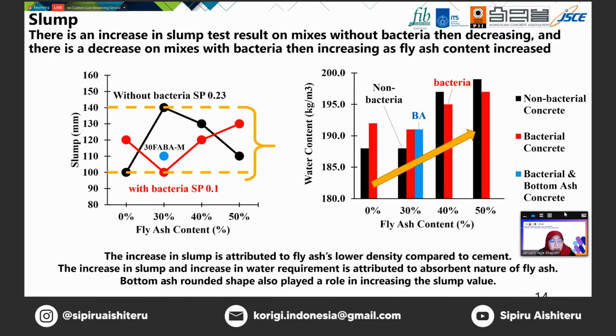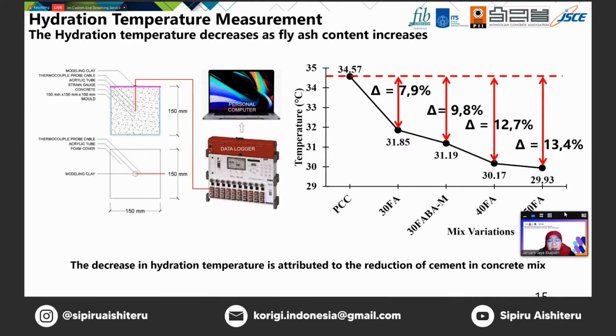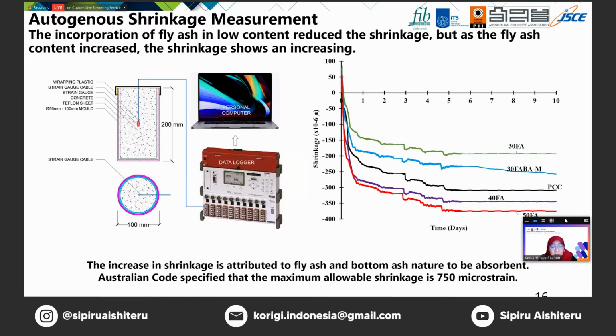And this is the result of temperature monitoring during 24-hour hydration. The ash helps a lot to decrease the temperature up to 13%. And something very interesting to see, I use my last experiment in Japan, at the University of Tokyo, to measure the shrinkage of concrete for 10 days.